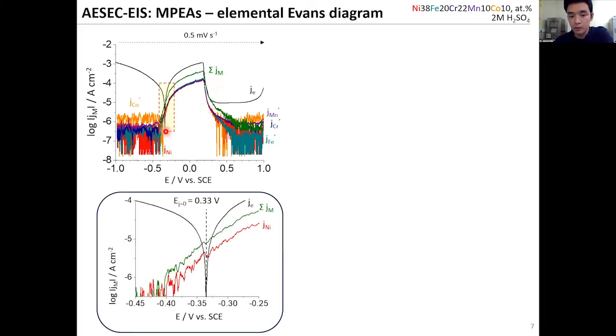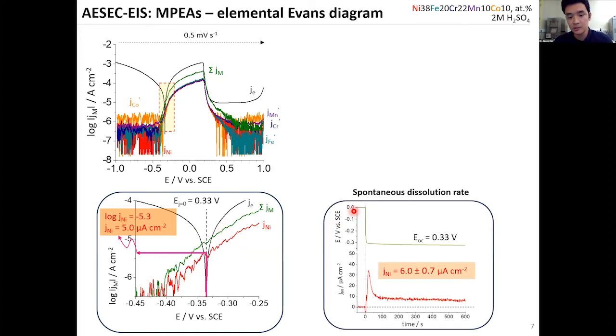So when we take a closer look at this Tafel domain, I would say near the J equals 0 potential, which is 0.33 volt, I put down the sum of all elemental current densities and nickel as an example. At this potential, we can extract the nickel dissolution rate, which is close to 5 microamperes per centimeter squared. What is interesting for us is to compare with the spontaneous dissolution of this high entropy alloy, but as an example, I only show the nickel here.